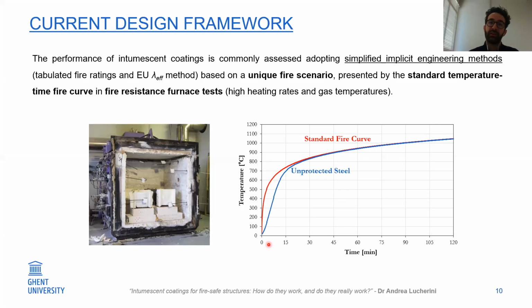So the steel starts increasing temperature due to thermal inertia, with a bit of delay compared to the gas temperature, and then, after reaching a certain temperature, starts following the fire curve. Instead, if you have a protected steel element, that could be intumescent coating, but also any material, you can see that the temperature rise in the structural element is actually delayed, and of course by different amounts depending on the different material.